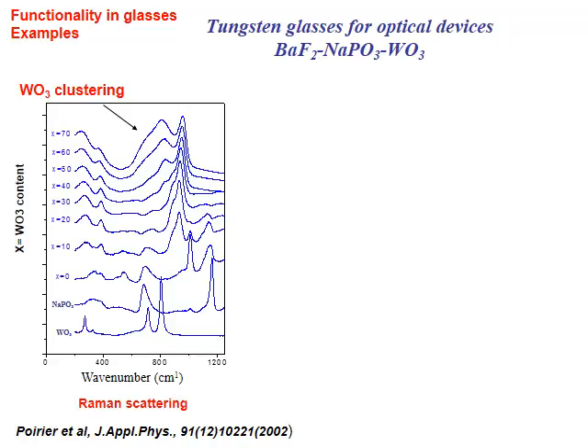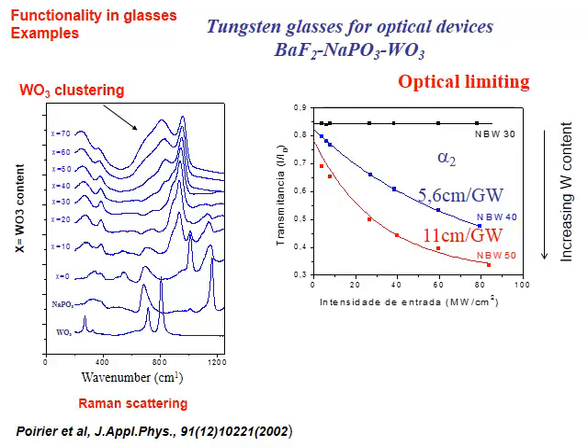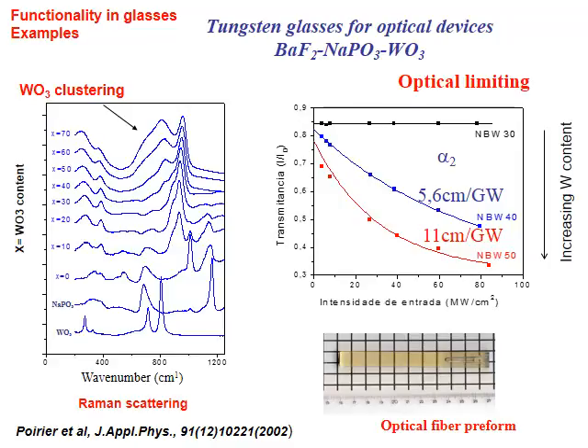An important consequence of this clustering concerns absorption of light. This figure shows transmission for green light as a function of the power of incident light. For low tungsten oxide contents, things look normal. That is, there is no dependence of the transmission on the power of the incident light. However, for higher tungsten oxide contents, a nonlinear behavior is clear. Glasses absorb more and more light as the light power increases. A clear application for these glasses concerns optical limiting devices. Moreover, these glasses are very stable against crystallization, allowing easy fibering.